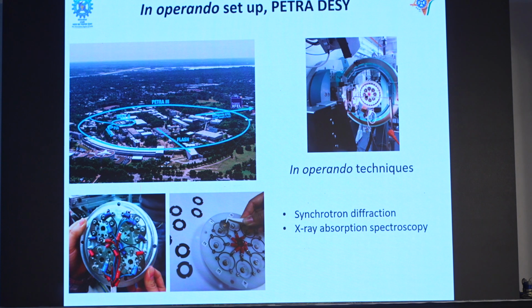We made an X-ray transparent cell, and we are putting it to a cell holder during rotation. And while the cell is connected to the electrochemical workstation, we are measuring the X-rays. We are passing the X-rays and we are measuring the absorption or diffraction.